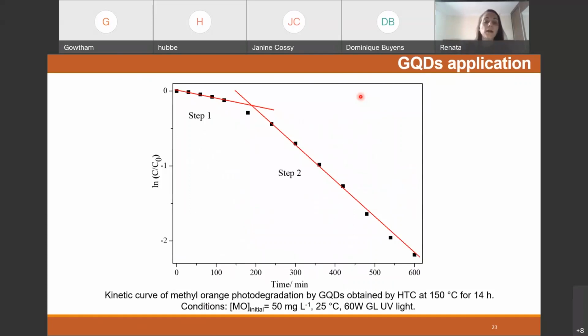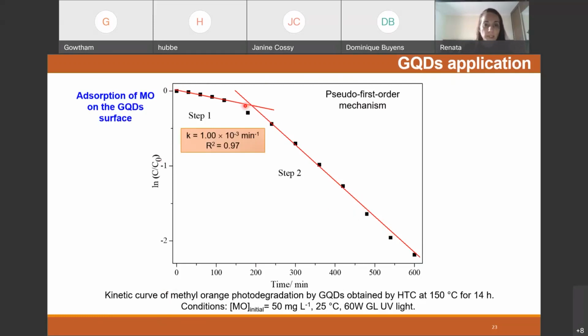We did a kinetic study of the degradation, and our data were adjusted to a pseudo first order mechanism, and it is possible to observe the presence of two stages in the process. Stage 1, because the slope changed, was attributed to adsorption of methyl orange on the graphene quantum dot surface, and this is the kinetic constant. The coefficient of determination was bigger than 0.9.